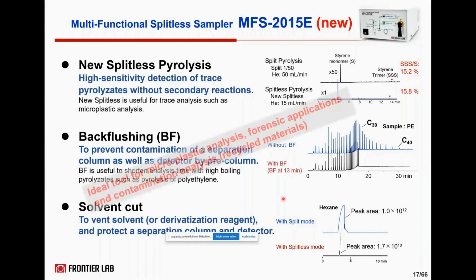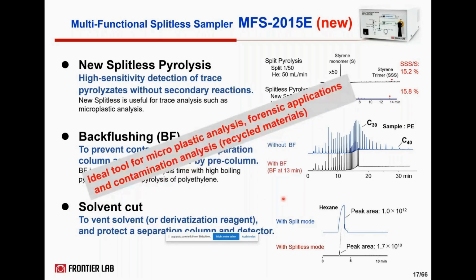The second feature is the backflush function. You can avoid that high-boiling compounds, which you don't need for the identification and quantification, reach the separation column. This would increase the sample throughput. As an example, you see the effect of backflushing after a certain time during polyethylene analysis. In addition, what comes with the system is solvent venting, so solvents will be vented by the system. I just want to emphasize again, we consider this an ideal tool for microplastic analysis, forensic applications, and contamination analysis, for example in recycled materials. It's ideal for trace analysis.